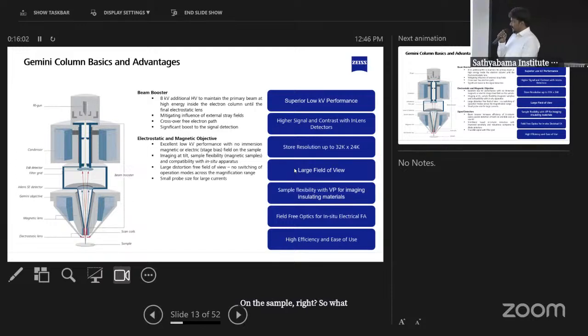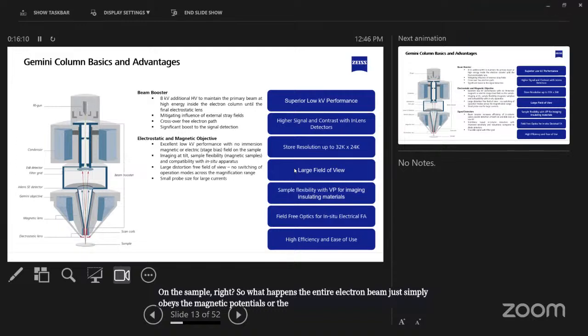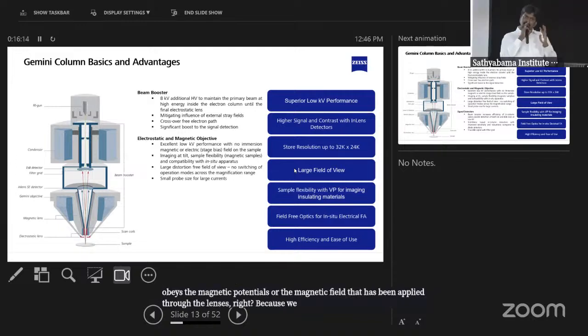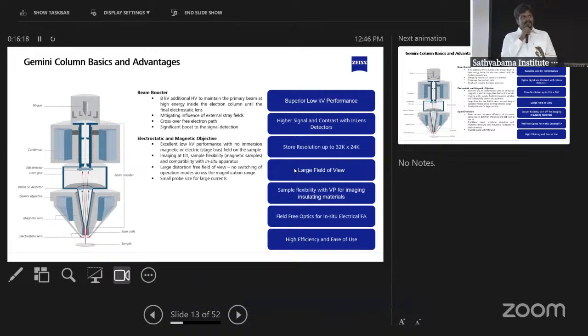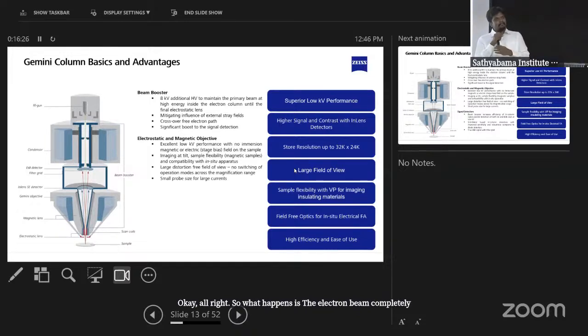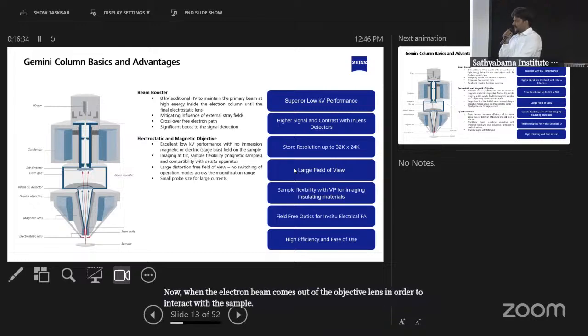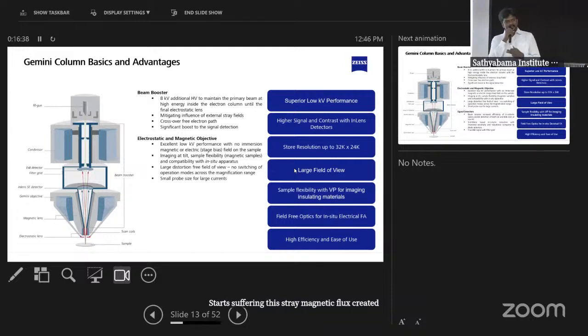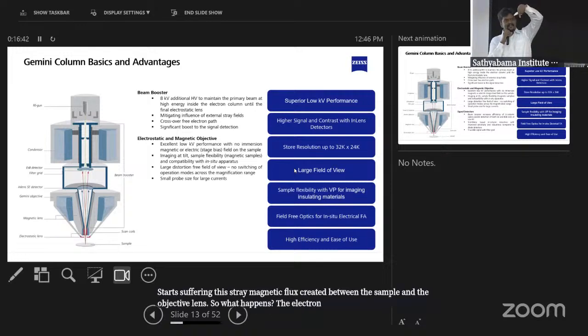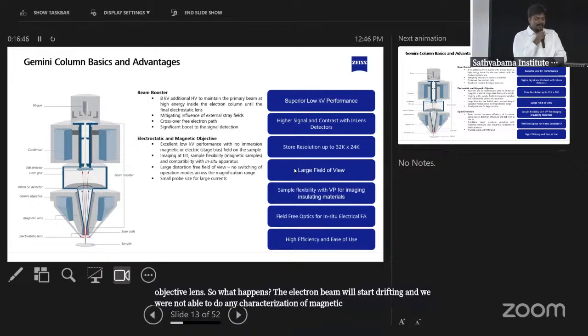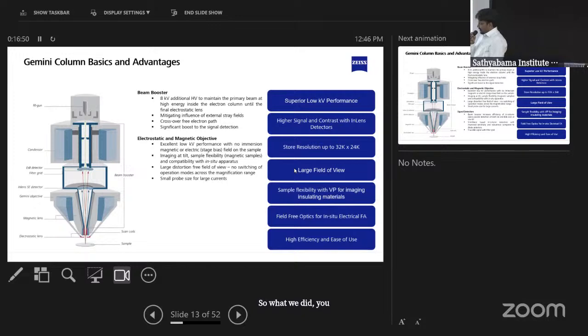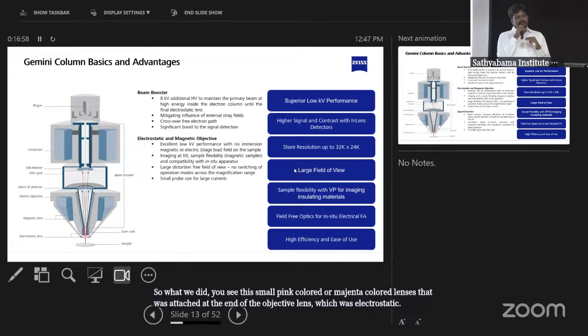So what happens? The entire electron beam simply obeys the magnetic potentials or the magnetic field that is being applied through the lenses, right? Because we understand the electric field is perpendicular to the magnetic field. Okay, you're all with me? All right. So the electron beam is completely controlled using the magnetic lenses. Now, when the electron beam comes out of the objective lens to interact with the sample, it starts suffering this stray magnetic flux created between the sample and the objective lens. So the electron beam will start drifting, and we were not able to do any characterization of magnetic materials at all. So what we did, you see the small pink or magenta colored lenses that were attached at the end of the objective lens, which are electrostatic. They are not electromagnetic, they are electrostatic.